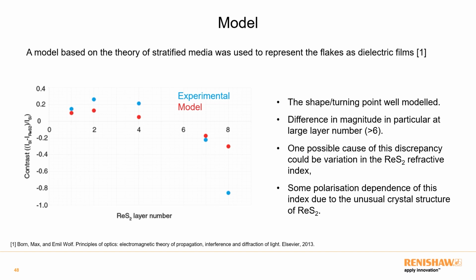We do have some discrepancies, particularly with the intensities. They're not bad, not so good at higher layer number, but obviously we don't have a huge number of points anyway. And it's likely that one of the discrepancies here is the change in the refractive index of the rhenium disulfide. We were able to get values for refractive index from literature, but we suspect there's some polarization dependence on this refractive index, and those values were not reported at the time we did this model.